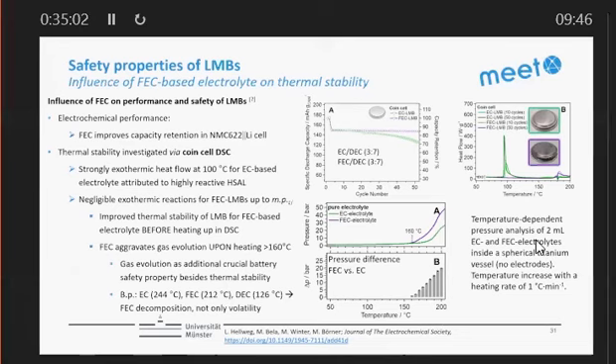And the bad news is that when you look at FEC and EC, they also have a decomposition temperature. The decomposition temperature is usually lower than the boiling point. All of these cyclic carbonates are decomposed into CO2 and something. Something in the case of FEC means, for example, also HF. And this is happening already at lower temperatures, typically around 100, 110 degrees C. This decomposition leads to a pressure buildup. So we made a temperature-dependent pressure analysis of 2 milliliters of EC and FEC electrolytes as they are in the cell, but without any electrodes. We put it in a pressure vessel and measured the pressure, and we see FEC gives us more pressure, so more gas evolution, than EC, and the pressure difference is already in the range of several 10 bars after the temperature increase. And as you know, bars in the cell means tendency to explosion, so you might have a problem there too. So FEC is good for cycling, FEC is good for thermal stability in the DSC, but FEC is not good for keeping the pressure low in the cell.